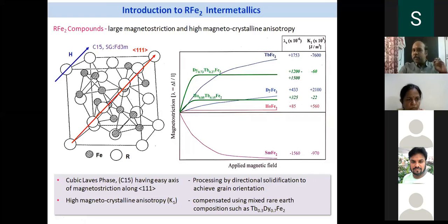As I told you, this material is an anisotropic material. That means its magnetic properties are different along different directions. So to have the maximum magnetic property, it is essential to orient this material. We don't actually want a single crystal in this material. We want some kind of grain orientation, or rather some texture is required in this material. That means I have a preferential orientation of the 111 direction along the length of the sample. And as I told you, the anisotropy is very high and it has to be compensated.